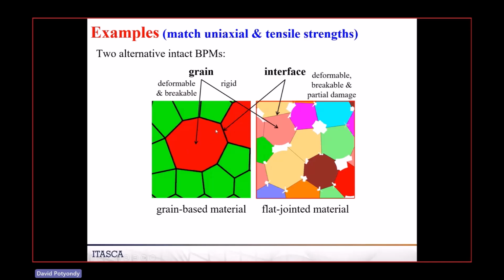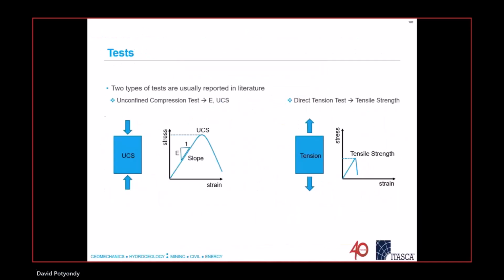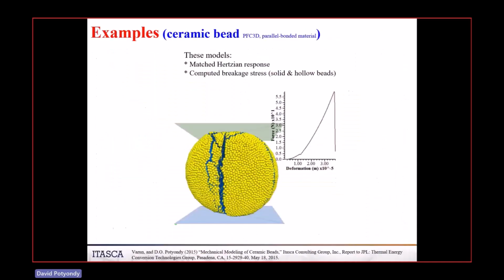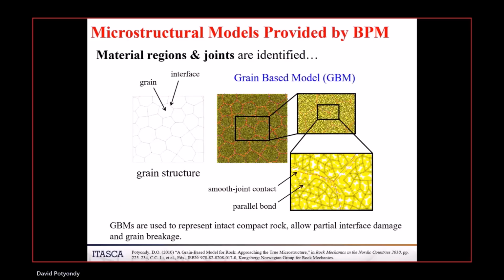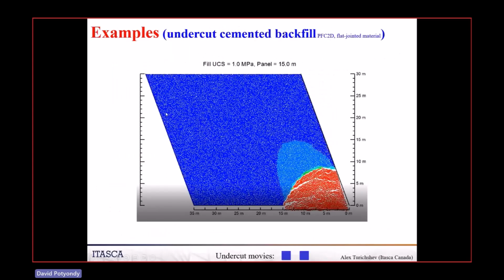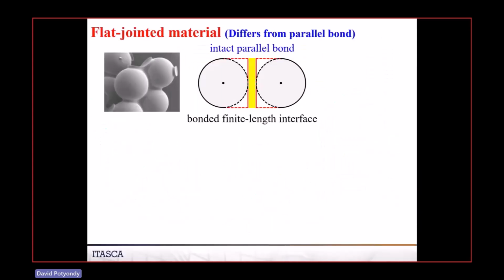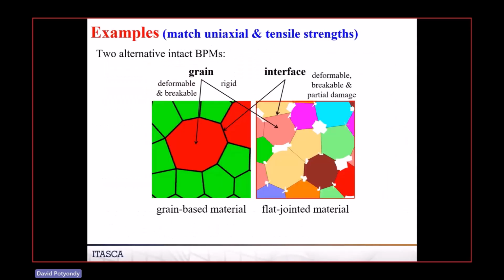So if you recall, the grain-based model looks like this here, where we take a collection of disks, we join them with parallel bonds, and then we overlay these joints on top. So we overlay a joint structure. And so inside of each one of these grains, there might be 50 or more parallel bonds, all of which can break. So we call that a grain-based model. So let's compare both of these. So what's the difference here?